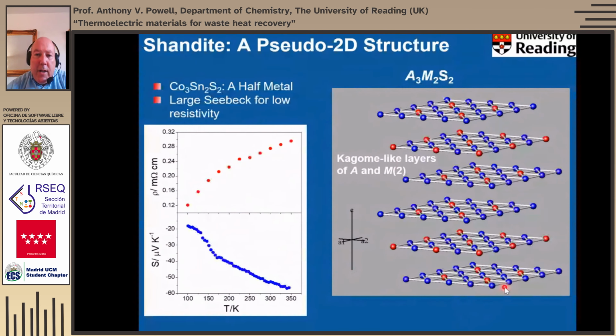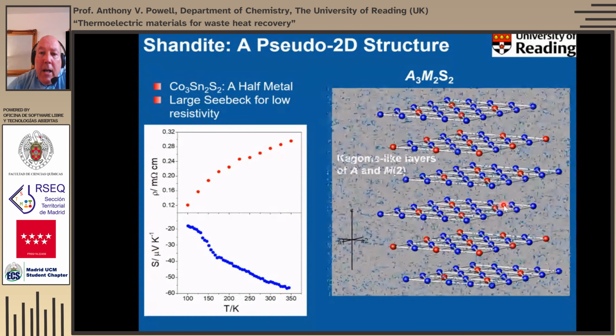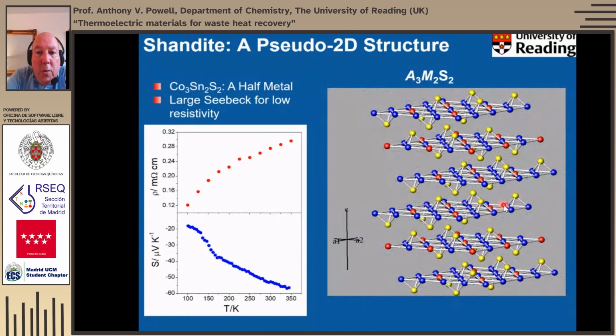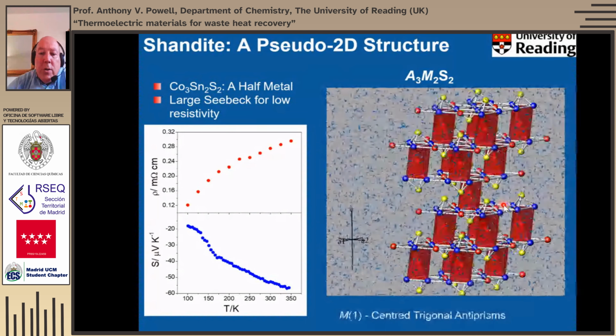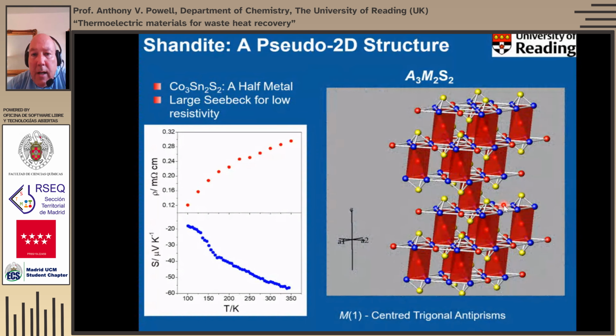It also has the attractive feature that although not low dimensional, it's pseudo low dimensional. So we have these Kagome-like layers here, these Kagome network type layers of cobalt and tin. The blue are the cobalt, so every Co3 triangle is then capped either above or below with a sulfur atom like that. Then the layers are joined together with a second tin atom, which is in a trigonal antiprismatic site. So we get this sort of pillared layer structure. So although not a true layered structure, it has low dimensional character.